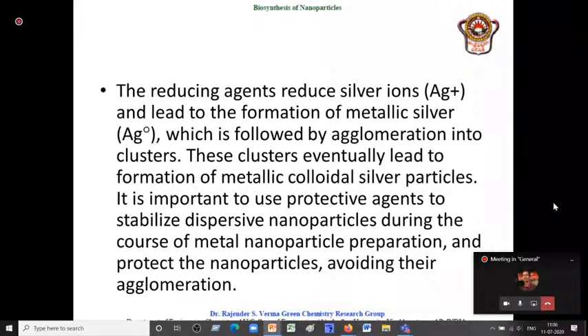for all metal nanoparticles, these metals are available with us in their salt form. Like silver, we have it in silver nitrate form, and it is in the Ag+ state. Now we need to reduce it so that it becomes Ag0. That's how we are trying to do it. Similarly, if you want gold, you take a gold salt and do the reduction reaction so that you have gold nanoparticles. If you have a platinum chloride salt, do the reduction reaction and you have platinum nanoparticles or palladium nanoparticles. If you have a nickel salt, you can convert it into nickel nanoparticles. If you have a copper salt, you can convert it into copper nanoparticles.